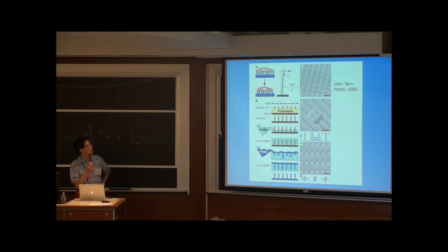So what we did was we basically made a device or a template that had vertical cantilevers. The way that you make these sorts of things, it's very difficult to make these things in rubbers, but it's very easy to do this in lithography, right? So we use this plastic SU8 where it's photo cross-linked. So what you do is you pour that material on top of a silicon wafer, because silicon is flat. And then you shine light through these little pinholes. The light then polymerizes a pillar.